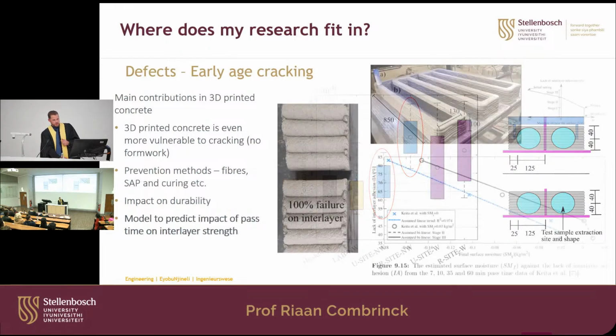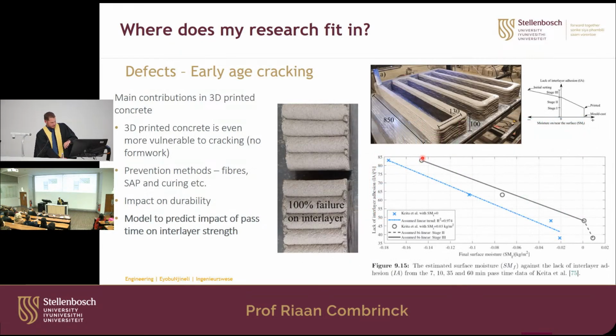Okay. Then we also looked at a model that actually predicts interlayer strength. And what happens is, as you go with your nozzle, you'll see the pass time differs. So as you print your concrete, the pass time differs. And if the pass time is too long, you will have a lot of water that evaporates, and that influences the porosity and also the strength. And we've developed this model that can predict the amount of surface moisture that is evaporated. Then you can see what is the impact on that interlayer strength that you're going to get, the reduction in it.